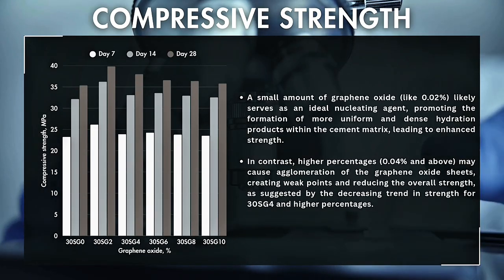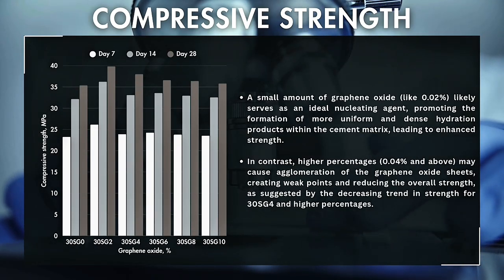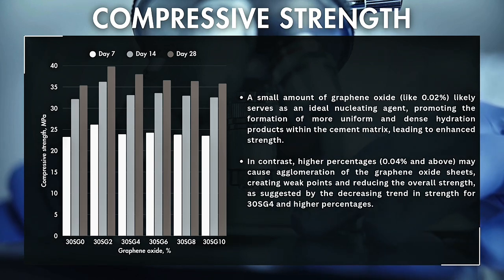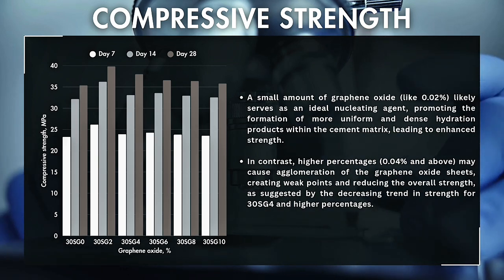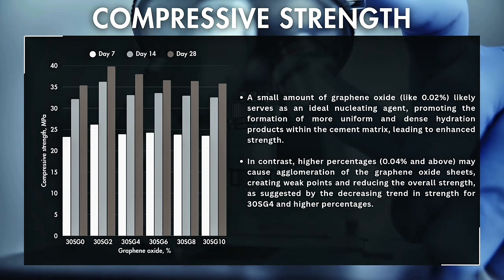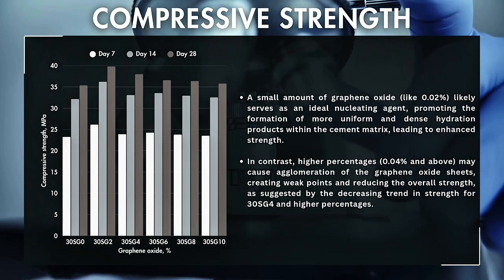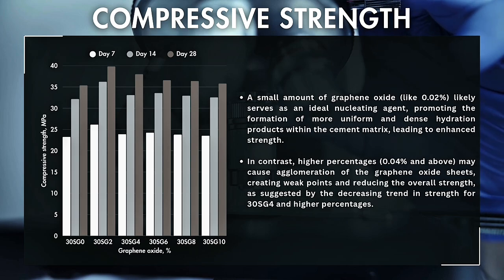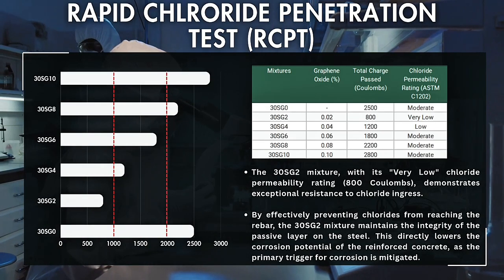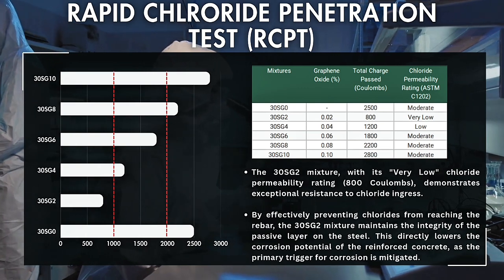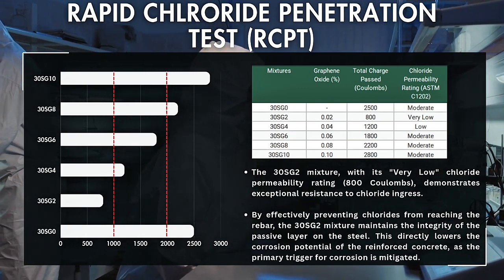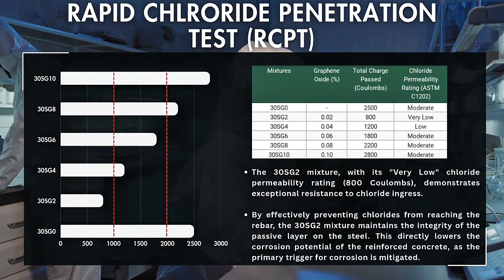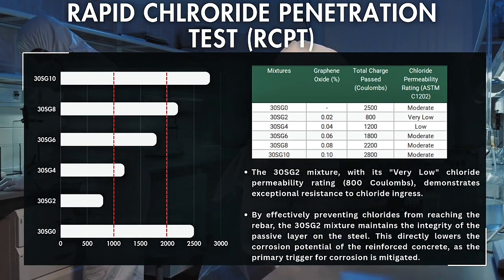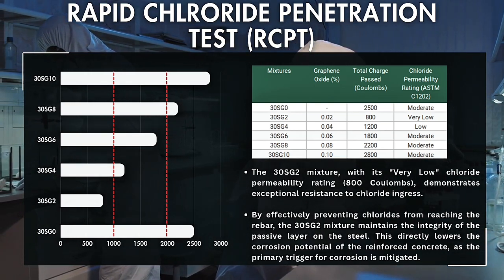Based on the provided information, a small amount of graphene oxide, 0.02%, works perfectly, making the concrete stronger and denser. On the other hand, using too much, 0.04% or more, causes the graphene to clump together, which weakens the concrete instead. Similar with the compressive strength, adding a tiny amount of graphene oxide, 0.02%, makes the concrete denser by filling tiny holes. This makes it much harder for things like salt to get through, which protects it from damage.